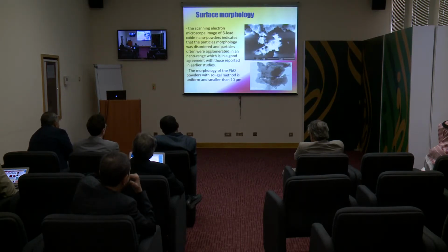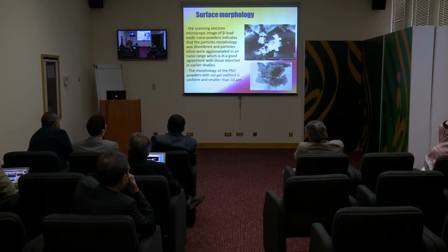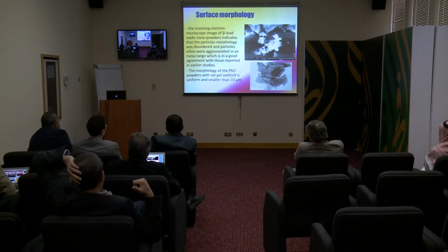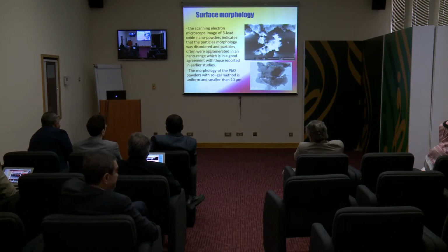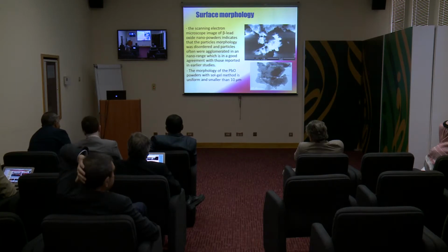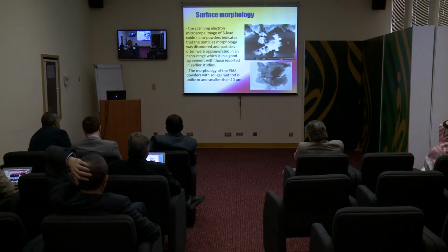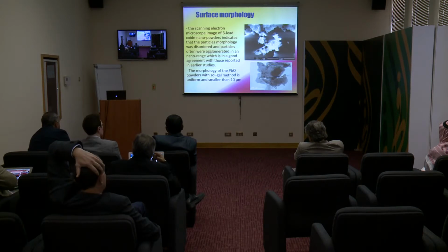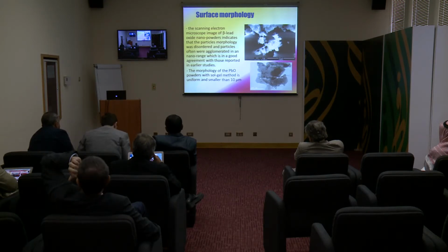Surface morphology starts with scanning electron microscope. Maybe the resolution and efficiency of the microscope is not high enough, but we have an indication from this image as follows. The particle morphology was disordered and the particles were agglomerated in a nano range, about less than 10 micrometers. The morphology of lead oxide powders with the sol-gel method is uniform, smaller than 10 micrometers.